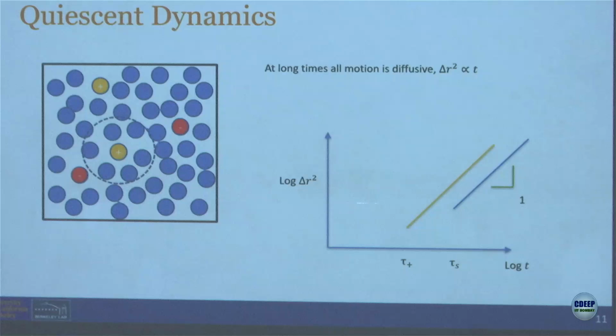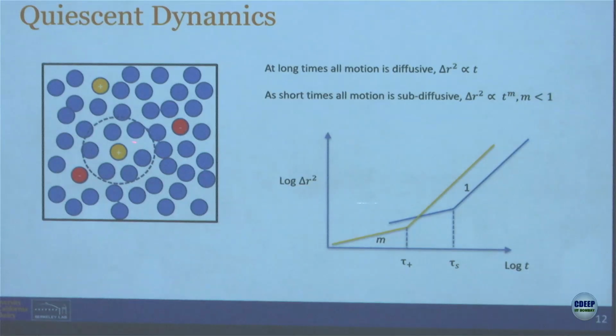But on very, very short time scales, the solvent molecules, for example, will feel the friction with the positive ion, and it will move with a lower slope. And this lower slope is what one refers to as the subdiffusive motion. And roughly speaking, this transition from subdiffusive to diffusive, this time scale is roughly the time scale that this solvent molecule hangs around the ion. And you can imagine that this is a very important time scale, because the solvent ion, in order to move across the electrolyte, has to escape from that cage.